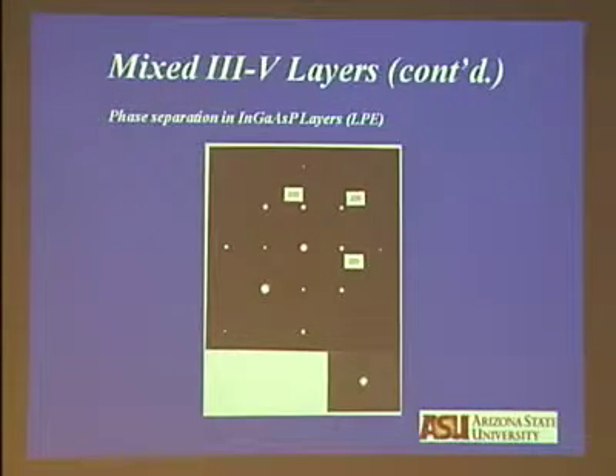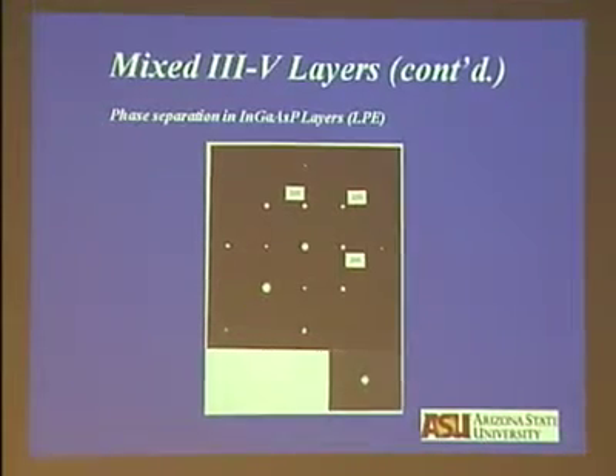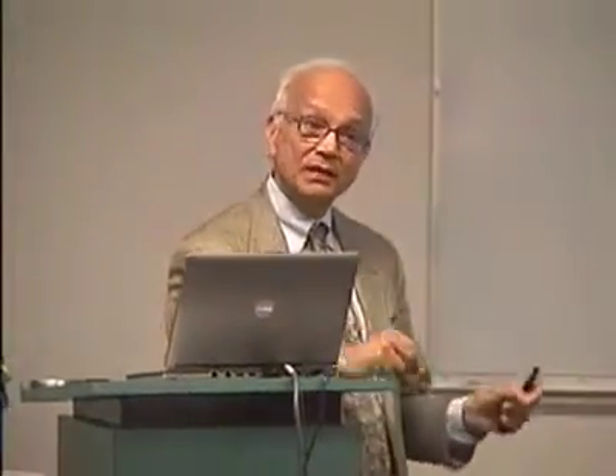Now, the next slide will show you how you determine the wavelength. This is the electron diffraction pattern from the 001 position. And what you see is, when you enlarge these spots, they are not circular. They have satellite intensity around the Bragg position. And from the position of the satellite with respect to the Bragg spot, you can determine the wavelength. Lipson did it in 1949 in a Proceedings of the Royal Society paper, so you can apply the idea. So when phase separation occurs, you produce satellite intensity. And the reason is that the indium-rich regions have a larger lattice parameter than the gallium-rich regions, and that I'll demonstrate, or argue, in the next slide. So there is phase separation in these materials.